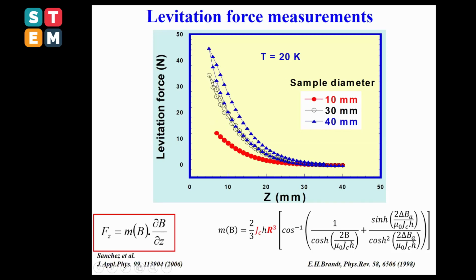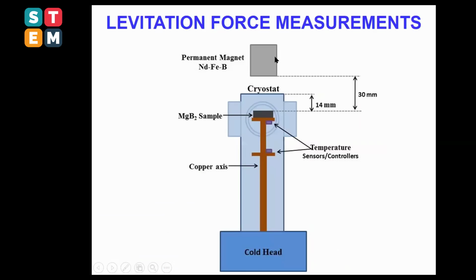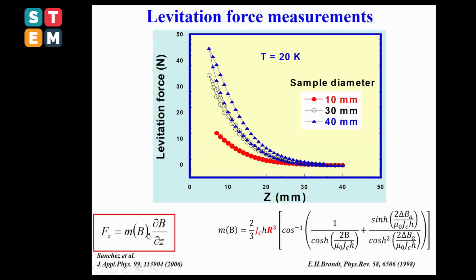Again, magnetic levitation force here is related to this formula, where you have the magnetic moment and the magnetic field gradient. This magnetic field gradient depends on the magnet that you have here on top. It's generated by this magnet. You can clearly observe, again, this magnetic moment depends on this Bean formula, which is related to the JC and also related to the sample size. This is the reason why you can clearly observe here the levitation force increase when you increase the sample diameter, up to 45 Newton in that case.